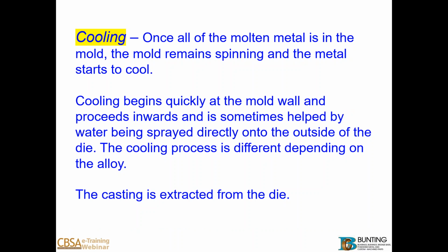So once the metal has been poured into the die, it has to be cooled with or without water. It's important because depending on how much water and when you put the water on, if you cool the metal too quickly, you can sometimes trap the impurities which you want to reach the ID. But cooling begins quickly at the mold wall and proceeds inwards, and is sometimes helped, as I said before, by water being sprayed directly onto the outside of the die. Also, using cooling or not using cooling depends on the type of alloy that you're casting.